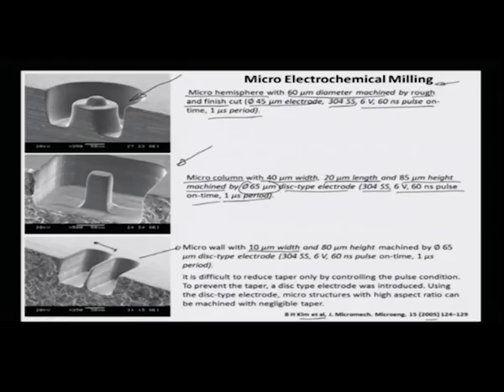So, this is close to 10 microns, and 80 micron height, which is this height right here, machined by a 65 micrometer diameter disc type electrode, again using the same material, 304 stainless steel, with 6 volt, 60 nanosecond pulse on time duration for a 1 microsecond period. So, one learning experience from this particular work is that it is very difficult to reduce the taper only by controlling the pulse condition, because electrochemical machining, as I think I have illustrated many times earlier, is a self tapering process.